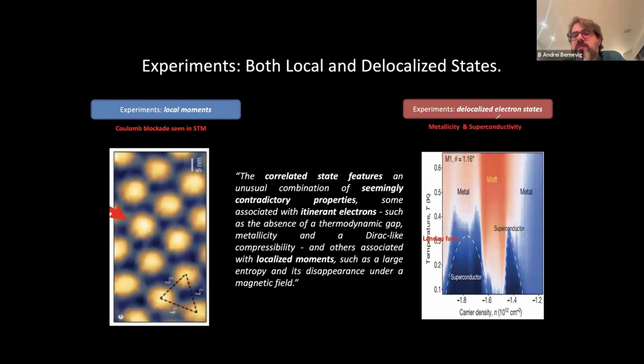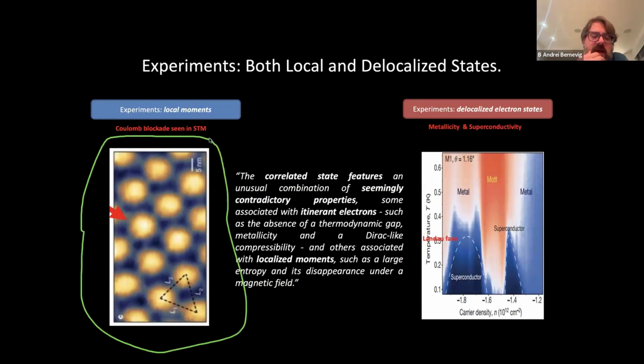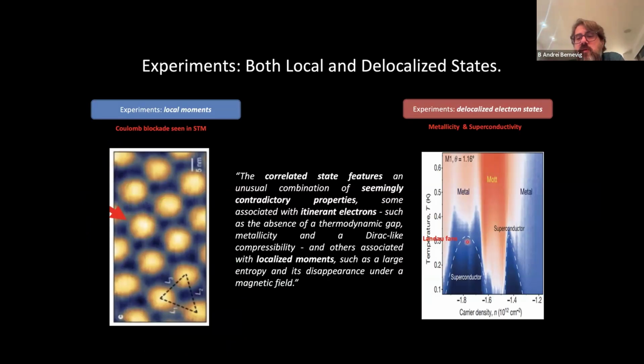Now, there's even more of a puzzle in this system, and this puzzle comes from taking quantum snapshots of the system. If I take an STM, this is Ali Yazdani, Eva Andrei, many other people who did STM experiments. This is the length of the Moire unit cell, roughly 10 nanometers at 1 degree, or 12 nanometers. But now you can see that with my Fermi level parked in these flat bands, the quantum picture of the system looks like it has localized states on the triangular lattice. So even though graphene has a hexagonal lattice, this looks triangular, and it looks like it's really localized electrons on the triangular lattice.